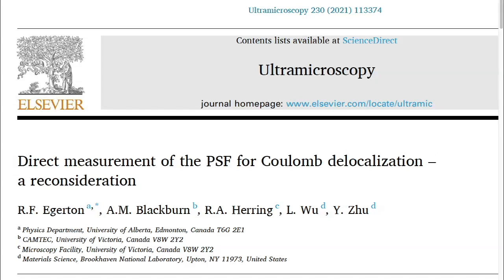The kind of thing I have in mind is what you see here. Our goal was to directly measure Coulomb delocalization by imaging a sub-nanometer STEM probe using inelastically scattered electrons. This seemed a good idea at the time, and aberration-corrected optics would make the anticipated effect measurable. The results were published as an M&M conference abstract, and they did not behave as expected. We ended up learning more about the instrumentation than about the physics. But the exercise did give us a better understanding of delocalization, so I decided it was worth publishing as a short note and as a warning to others.